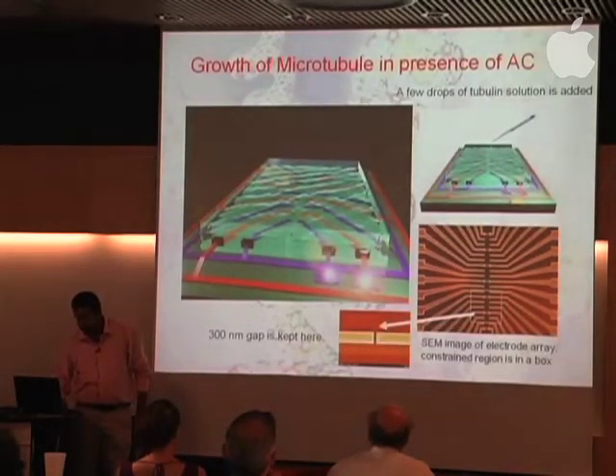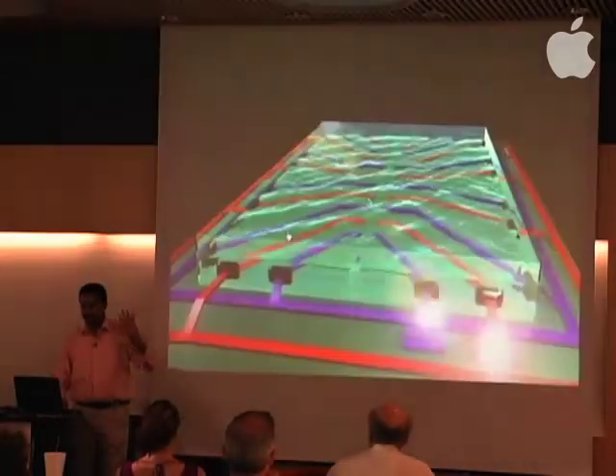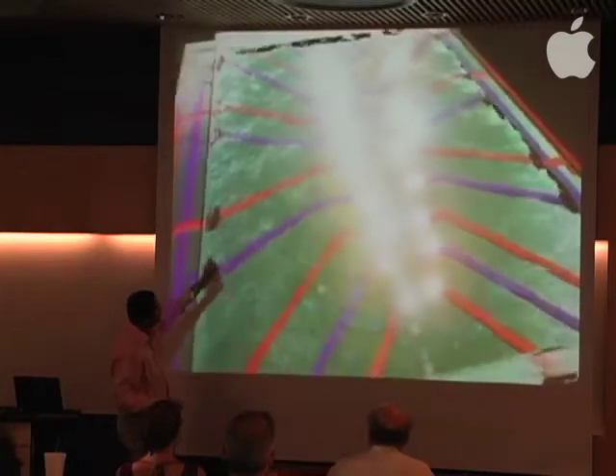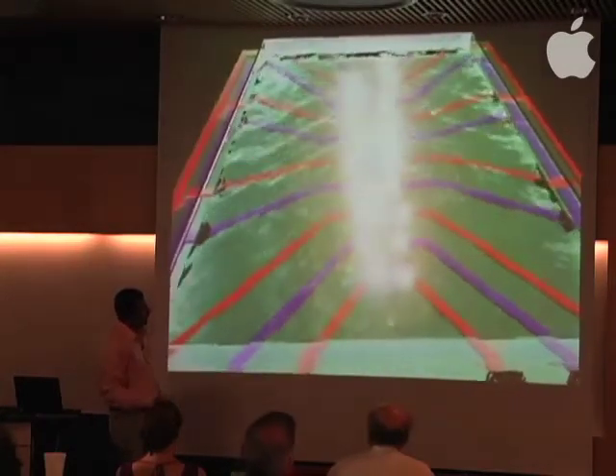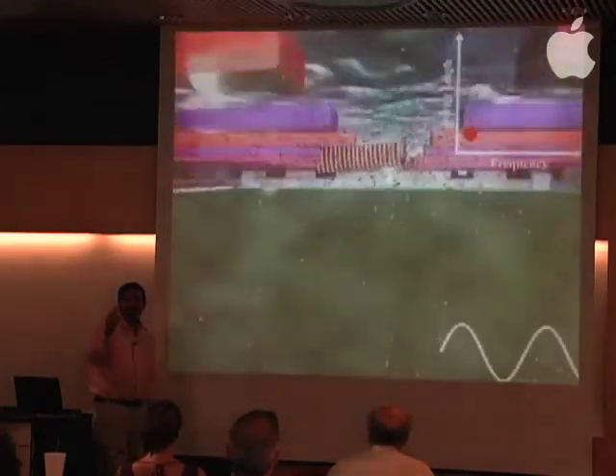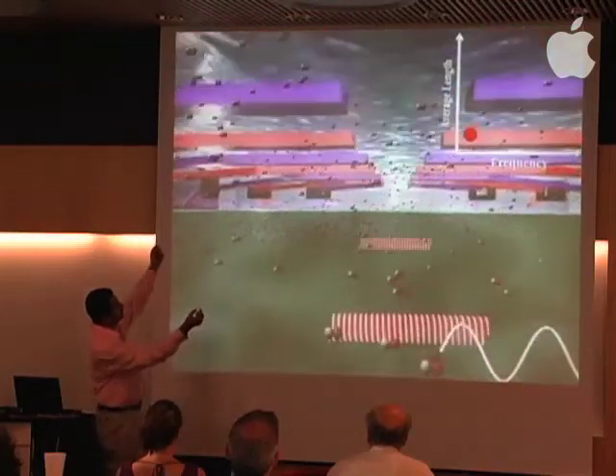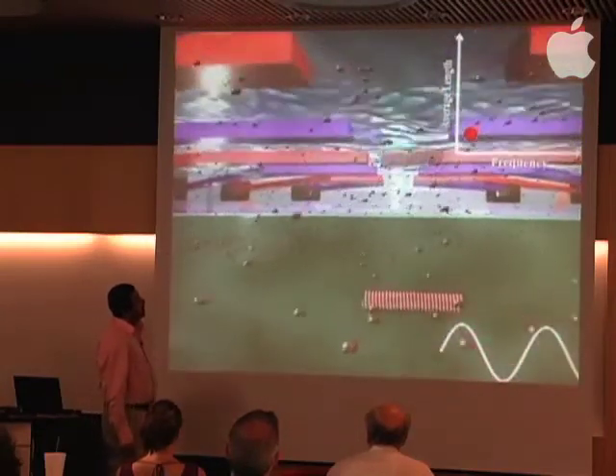So this is a schematic overview, but the setup is not very complex. If you want, you can do it in your laboratories also, even small school laboratories. So you have blue is negative, red is positive. Say we have electrodes coming out in a heat bath, a water bath, say at 37 degrees Celsius. And we apply just an AC signal. And microtubule grows spontaneously and falls down.